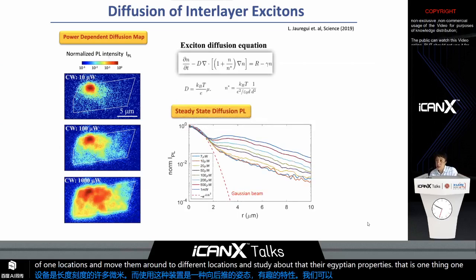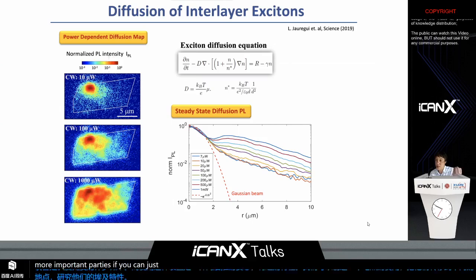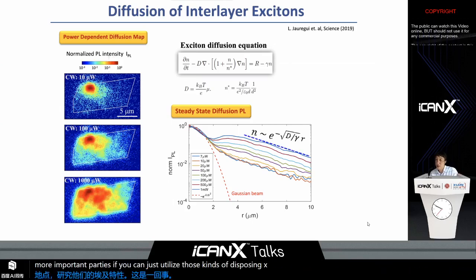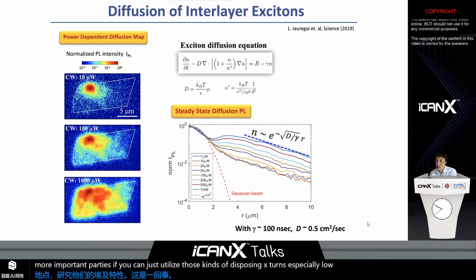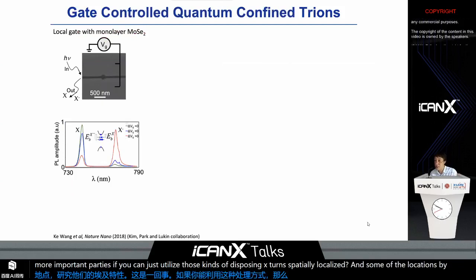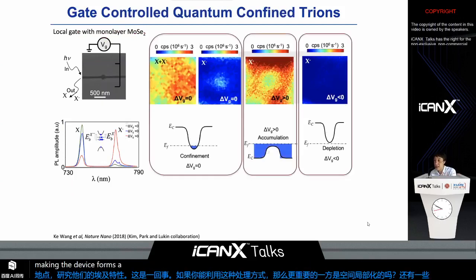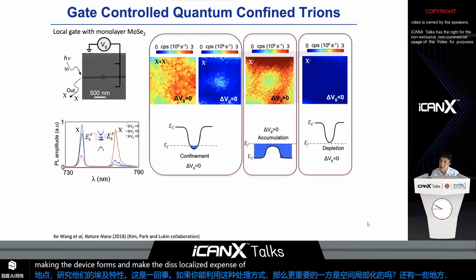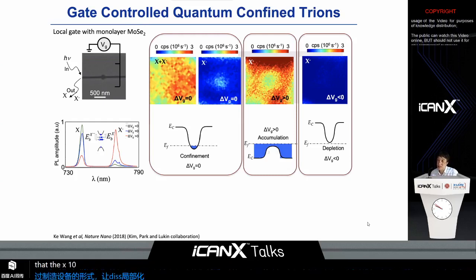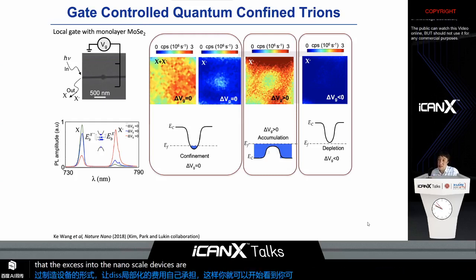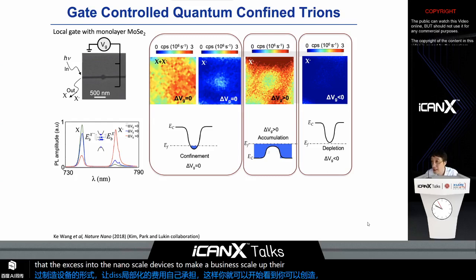But the more important part is that we can utilize these dipolar excitons to spatially localize them at certain locations by shaping the device, making these localized excitons start to emit by themselves, right? So you can start to see that you can put excitons into nanoscale devices to make nanoscale optoelectronic devices.